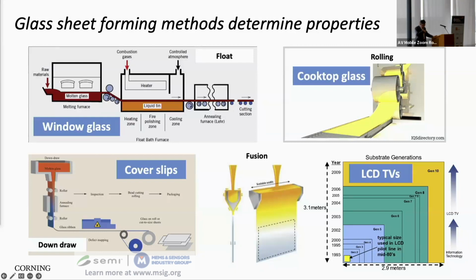And then on the bottom left is a very thin glass that we can draw using what's called a down draw process. You can actually see the brownish looking glass going through a slit, and then it forms a sheet. The downside of that is the glass is in contact with the inner walls of the slit. So sometimes there's imperfection coming from this contact. And bottom right is what's probably most relevant to this community. This is Corning's fusion process.